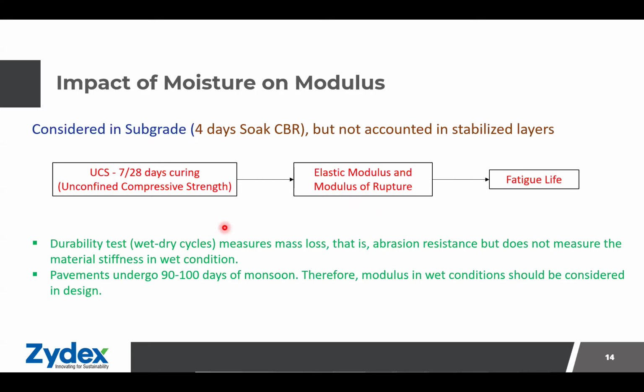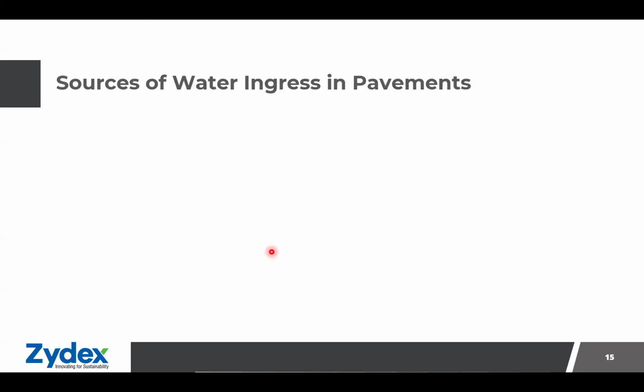Also, we have a durability test that accounts for the moisture impact, but durability measures the mass loss. That is, it is really abrasion resistance and does not measure the material stiffness in wet condition. Our pavements undergo 90 to 100 days of monsoon. Therefore, modulus in wet conditions should be considered in the design.